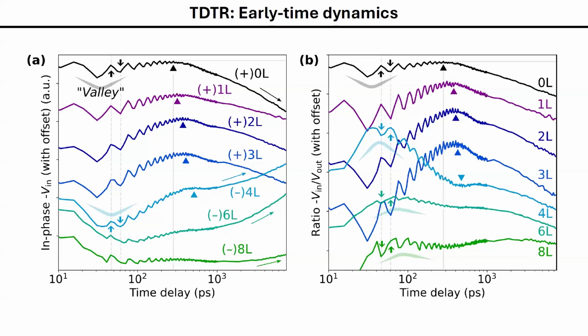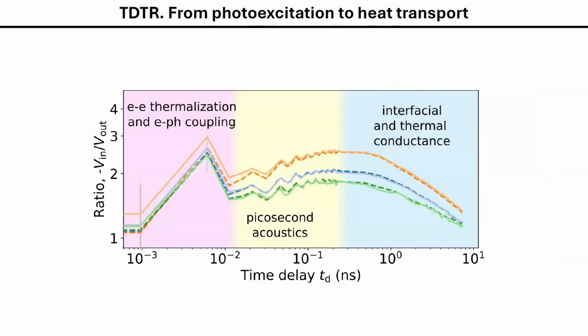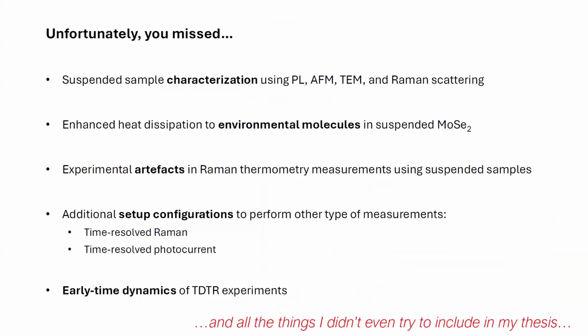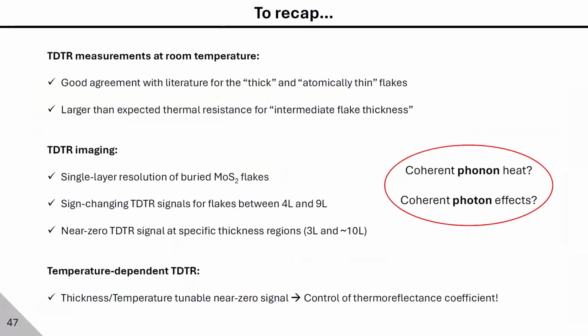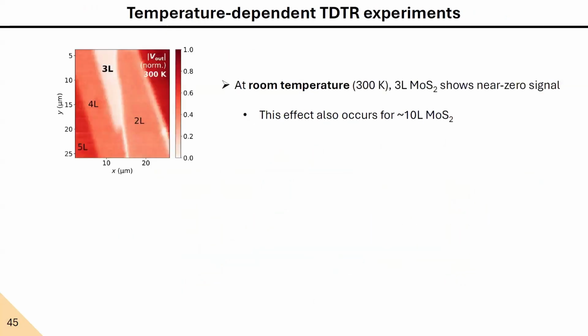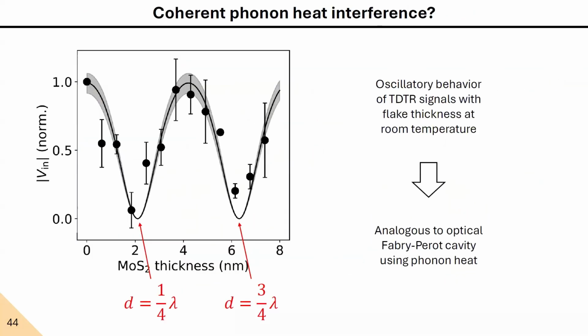Okay, just moving to the coherence effects of phonons. You were doing the analogy of a Fabry-Perot, yeah, and so there, are you taking a distribution of phonon modes to reproduce this? Can you comment on that? This is a very good question because, of course, here we retrieve one single wavelength for all these samples. Of course, the wavelength may change with thickness. And of course, heat transport is a broadband process. There are many phonons contributing to this. So this would be an averaged phonon wavelength, let's say. Okay.